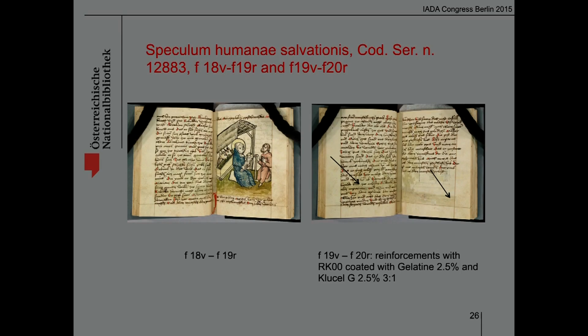2 years after the treatment, the reinforcements are stable. In the case of 2 objects with strong degradation of verdigris, we decided to apply the copper complexing agent BTA locally by brush from the verso. In the conservation of manuscripts, and you see one example on the screen, and one incunabula, we limited the treatments to mechanical stabilization of damaged paper with pre-coated papers.